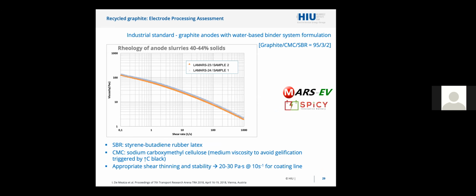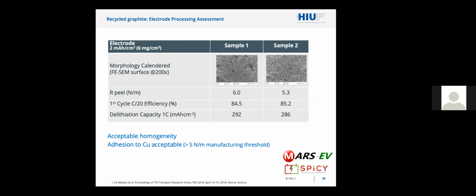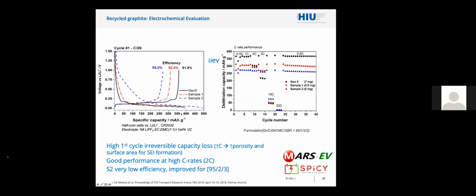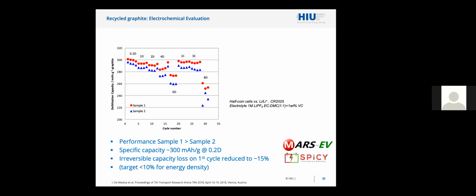So it is possible to process them using the typical CMC SBR composition, and this slurry has appropriate rheology for coating. We can make new electrodes and test them. You see that depending on the cell, we get different performances, but we can still get decent Coulombic efficiency, for example, with the generation 0 cells, and also good capacity out of these cells. So it's clear that it is possible to recycle graphite rather than burning it, and direct recycling of material is definitely extremely important.